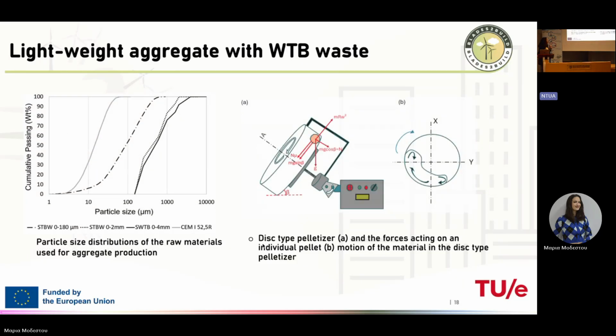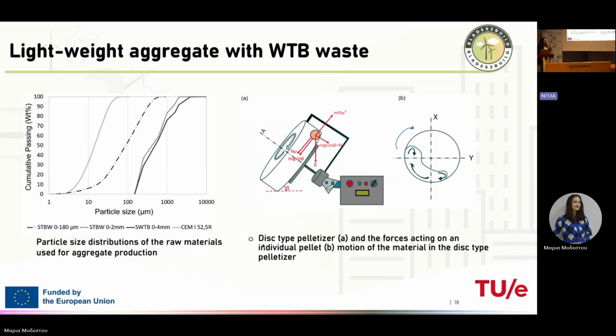So this is the particle size distribution of the raw materials we used. We used wind turbine blade waste of fine size, because, as you saw in the previous images, we have a lot of powder and small fibers, almost 40% of this, regardless of the upper size of the waste. So we had 3 sizes of waste: up to 180 microns, comparable to cement, up to 2 millimeters, and up to 4 millimeters. And we have some rapid hardening cement. And we use a disc type pelletizer. We visualize it to make it nicer, with the forces acting on individual pellets.